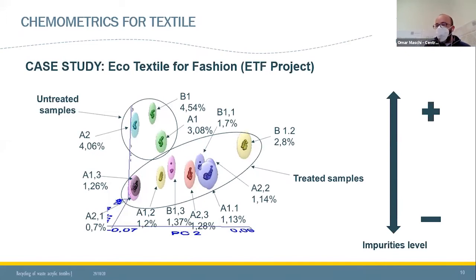If I have to evaluate the impurity level of a material, and I have developed this kind of model, I don't need to perform a chemical analysis. So I don't need 2 days to have an evaluation of the impurity level of the material. If the model is very good, this prediction is very close to the real amount, and I can have an evaluation of the impurity level without chemical analysis, but just with a more or less 20-minute analysis with NIR spectroscopy. So I can obtain an evaluation of the impurity level that is very important for the optimization of the preparation process that the material needs before, for example, dyeing or finishing.